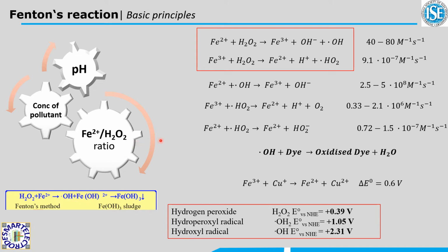There are 5 main reactions governing the total rate of the breakdown. The first 2 produce highly oxidative hydroxyl and hydroperoxyl radicals. Hydroxyl radical is much more desirable since it has much higher oxidation potential. The other 3 reactions scavenge these radicals, reducing the efficiency of the main reaction, the oxidation reaction. Also, since we are using copper foams, copper corrosion also occurs. Copper ions can help to regenerate the very desirable iron 2+ ions, which help to generate the hydroxyl radicals.